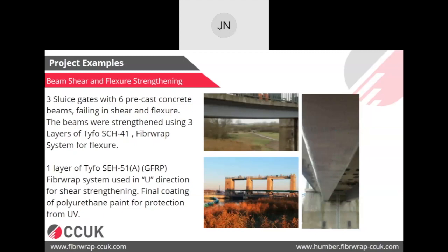That was done using FRP, and we did that work from the MEWP. So we didn't need scaffolding or anything, so we saved a lot of time on the scaffolding, and then did one gate in 1 week. So in 3 weeks, this whole structure was strengthened. Probably 3 weeks would have been the time they needed to put the scaffolding up there. So again, you see the time you've saved there, and how quickly they were able to use this structure by doing it with the carbon fiber strengthening system.